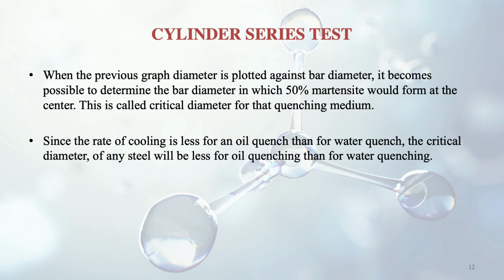Since the rate of cooling is less for an oil quench than for a water quench, the critical diameter of any steel will be less for oil quenching than for water quenching. Yes, it is quite obvious, because the rate of cooling in oil is lower, so less martensite will be formed. So when we make a cylinder out of that martensite, its diameter will obviously be smaller.